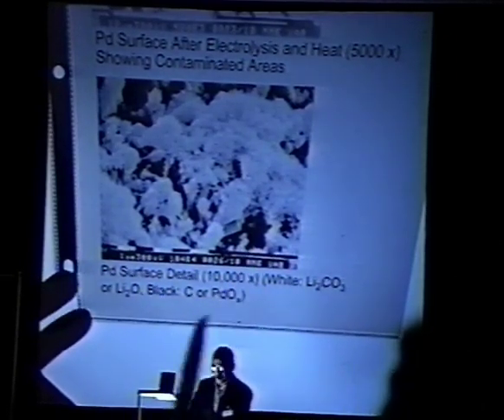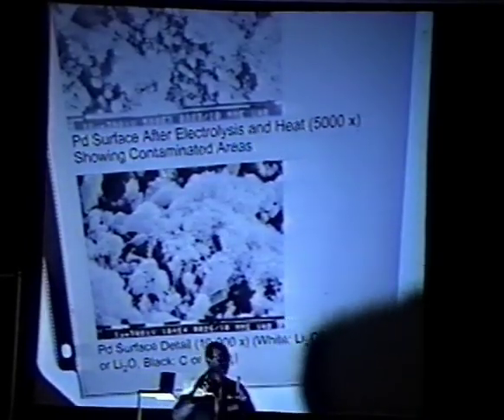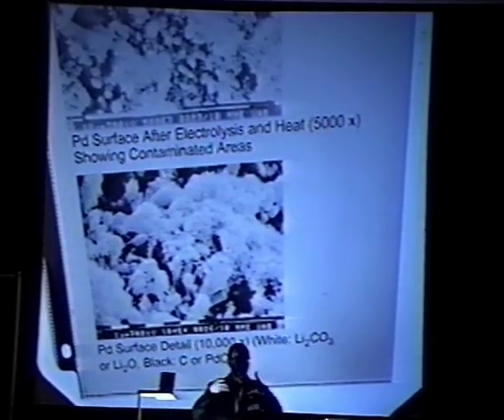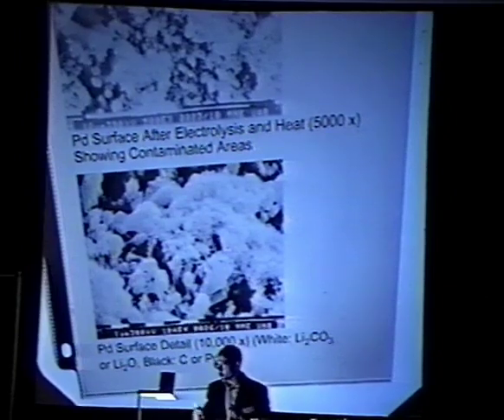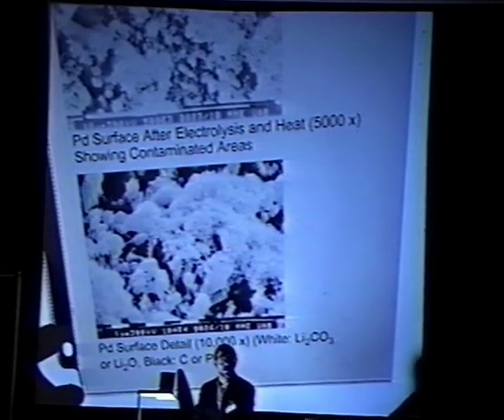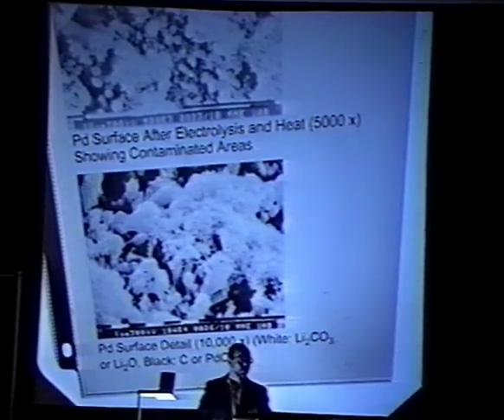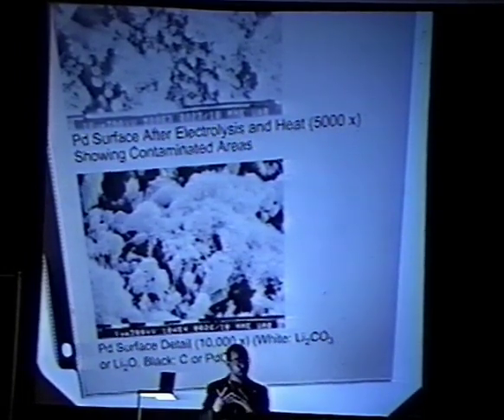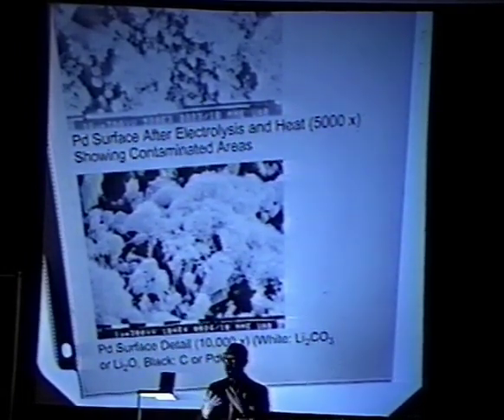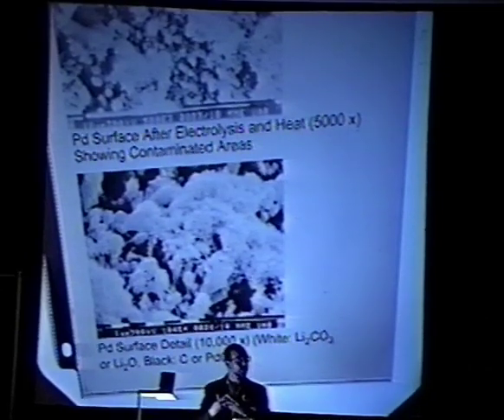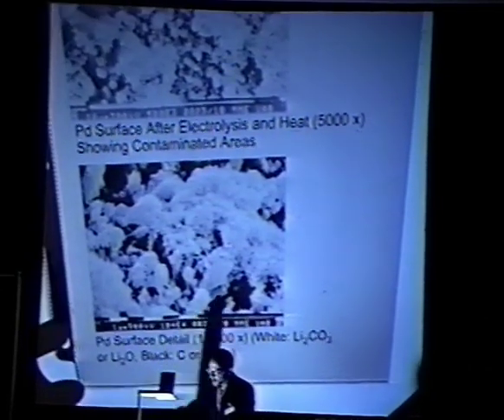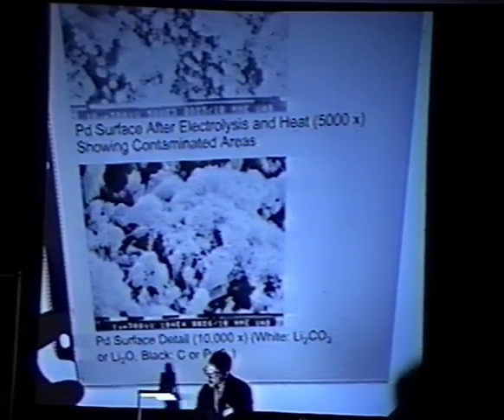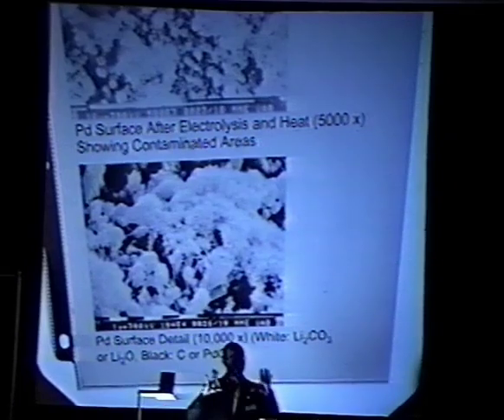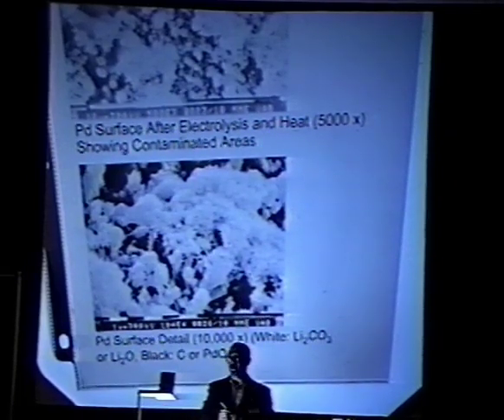The black material, remember the photo I showed you where it looks black. In fact, when it first comes out, it looks like it's been in a barbecue pit of sorts. The black is apparently carbon and palladium oxide. Those are the two things that make this look dark. Then up close under a microscope, you see a lot of this more white crystalline structure on top of it. Again, on this magnification, there's 10 microns right there. So these are very large pieces that we're looking at. A lot of lithium carbonate that's stuck to the surface.